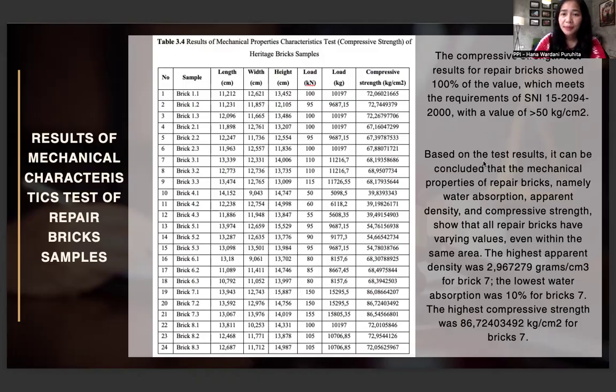All good. Based on the test results, it can be concluded that the mechanical properties of repair bricks, namely water absorption, apparent density, and compressive strength, show that all repair bricks have varying values even within the same area. The highest apparent density was 2.96 grams for brick 7. The lowest water absorption was 10% for brick 7, and the highest compressive strength was 86.7 kilograms per centimeter for brick number 7.